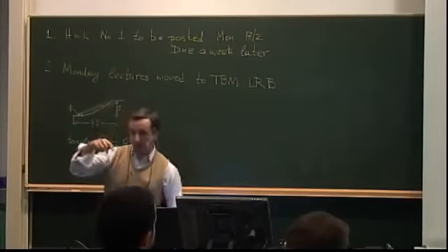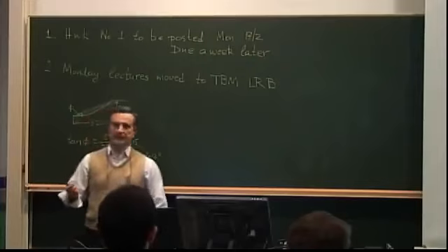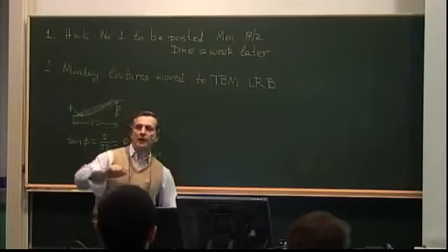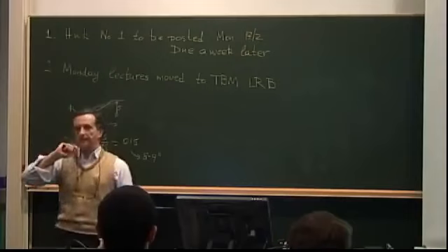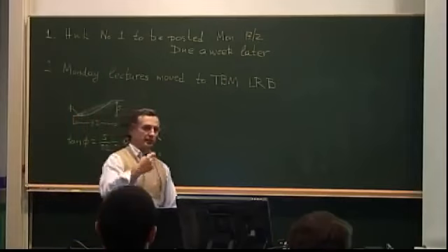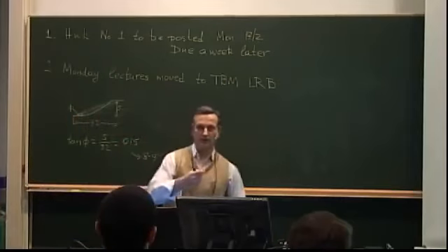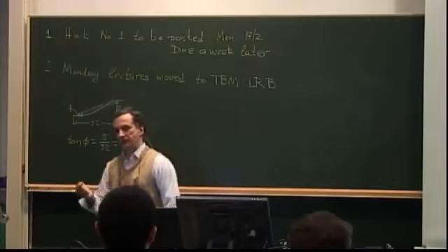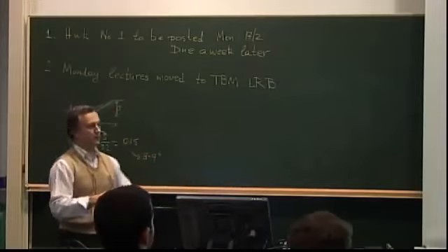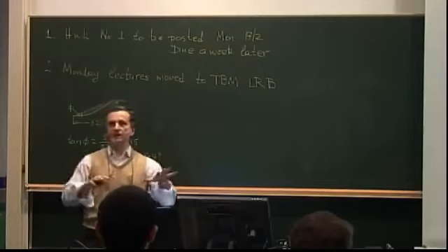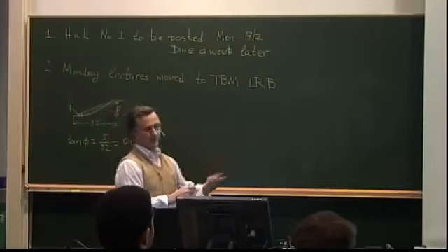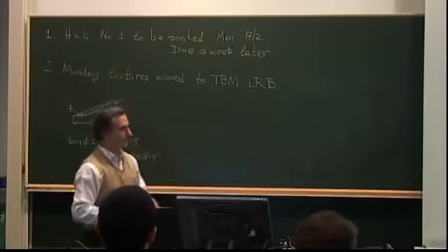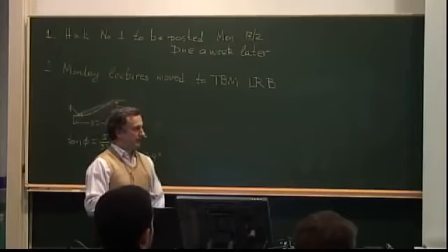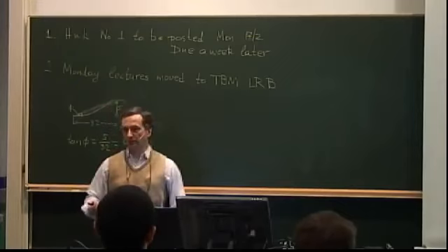Now, the fibers do not all have the same strength. In addition, there are local defects. There are some fibers which have surface scratches or cracks, or the bond with the matrix is not strong enough, or the distribution of fibers is not even enough. So you end up having a lot of matrix or a lot of fibers in one location versus another. In the end, no matter how you look at it, one fiber will break first.